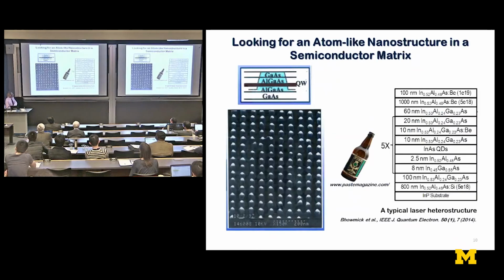So the simple-minded way to get a quantum dot, and I'm talking about the very early 90s to mid-90s, was to grow epitaxially a quantum well structure, as you see that, and if you can etch it down through a mask, you can then possibly get an array of such quantum dots. Now, in those days, in our facility down the road, we had an E-beam system, but it wasn't as good. So I sent my student then and my colleague now, Jamie Phillips, to Clivia Sotomayor Torres in Glasgow. She's now moved to Germany. She had the best electron beam facility in the world at that time. So I sent Jamie there, and he came back with these beautiful arrays of quantum dots.